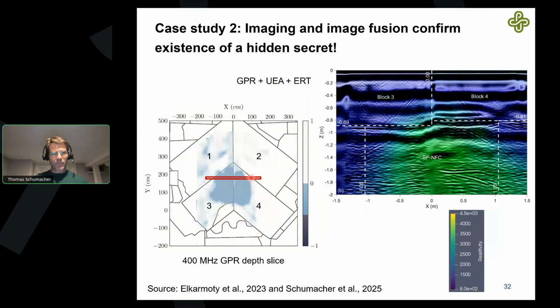So I'm showing here a view of the chevron again. There's a horizontal cross-section that I'm showing here on this side. This unites all 3 measurements. In this case, we fused the images from GPR, ultrasonic, and electrical resistivity tomography together. We could see very strong reflectors here in 2 locations, around 90 and a little bit more like 80 centimeters. And then behind it, there's this big high resistivity volume, high resistivity indicating that there might be air. On this side, you see the reflector. This is based on a GPR measurement.